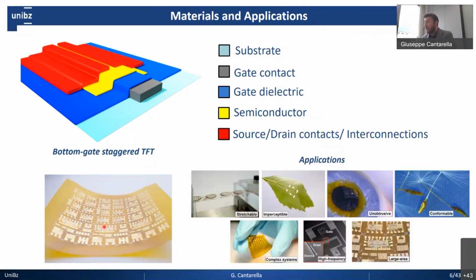During the years, my colleagues and I have worked towards different applications. So, for example, as you can see here, the employment of stretchable rubbers as a substrate allow us to go towards stretchable applications. What you see here in the middle, imperceptible and unobtrusive, consists in the employment of highly transparent materials. So we change our gates, our electronic stack in a way to achieve highly transparent applications and highly transparent electronics. Conformable electronics consists in having all the electronic stack, including the substrate, incredibly thin, sometimes even below 5 micrometer, to achieve a perfect conformability around any surface.